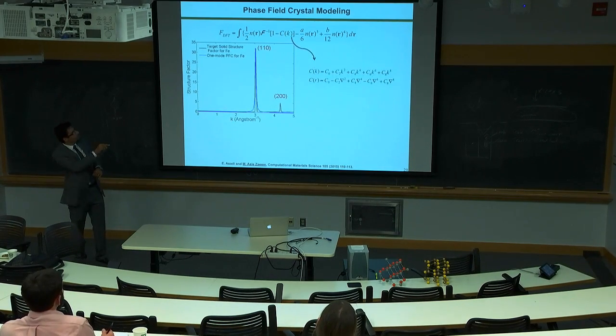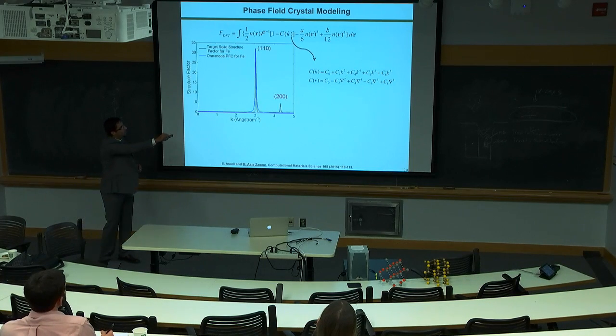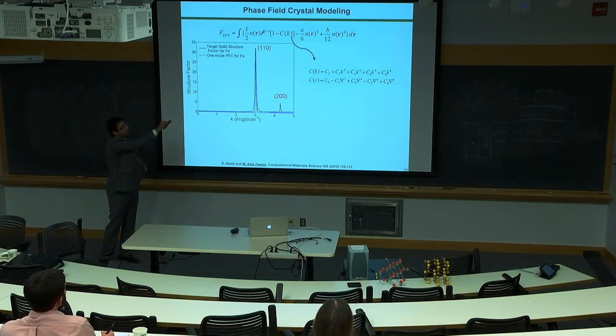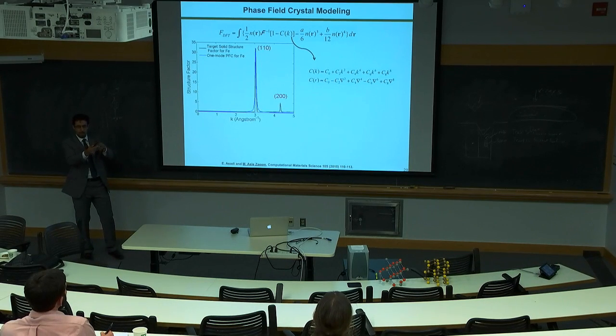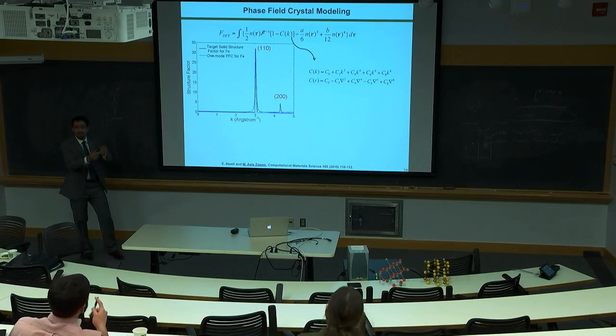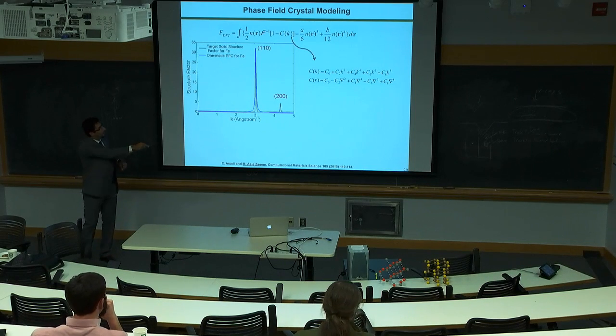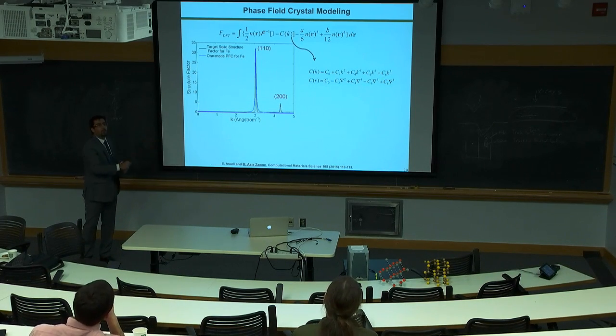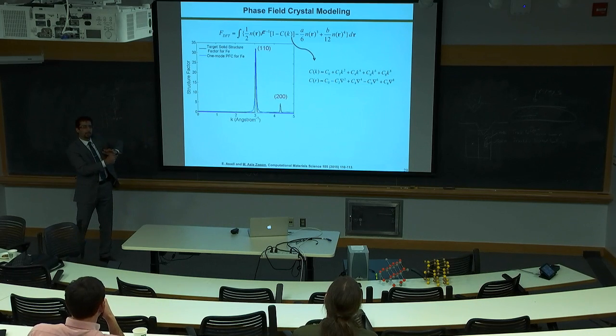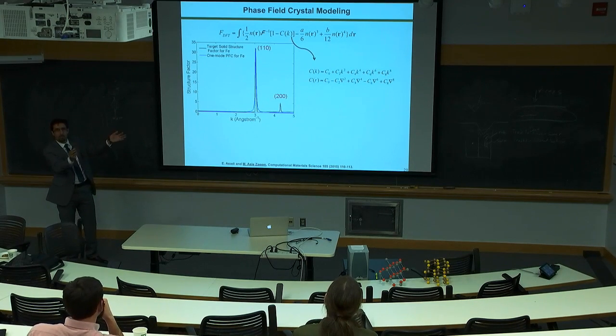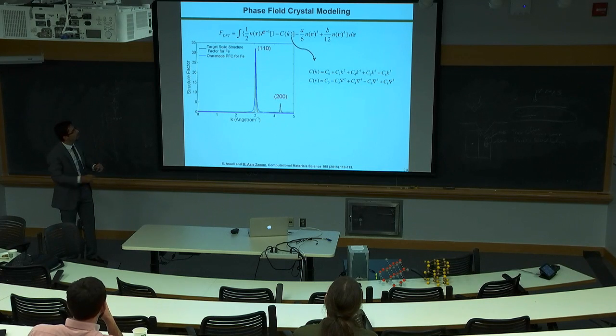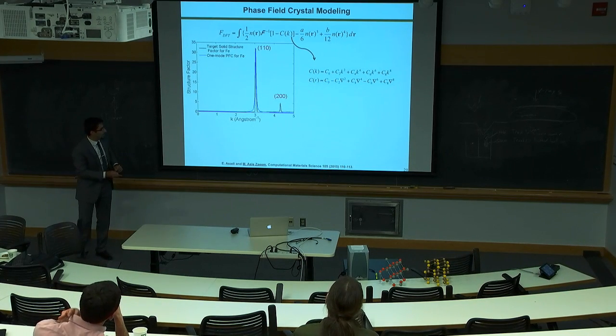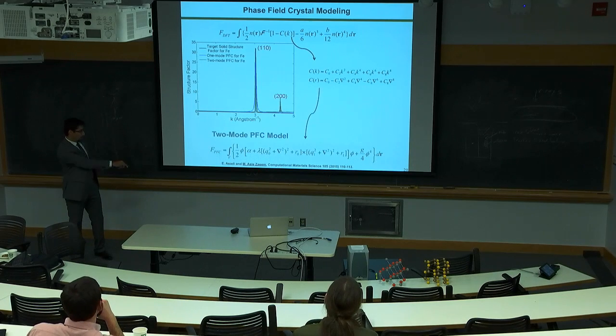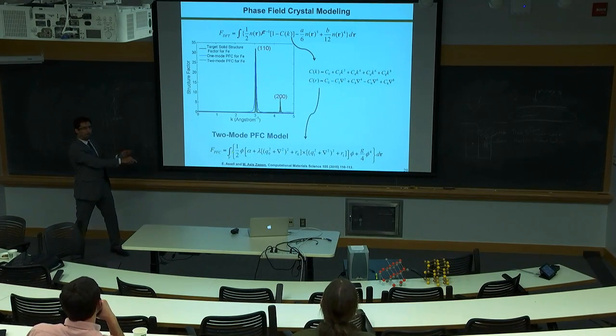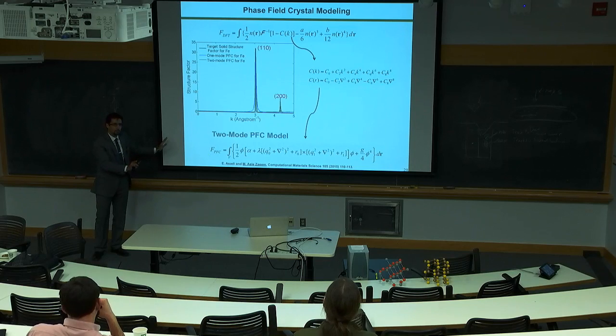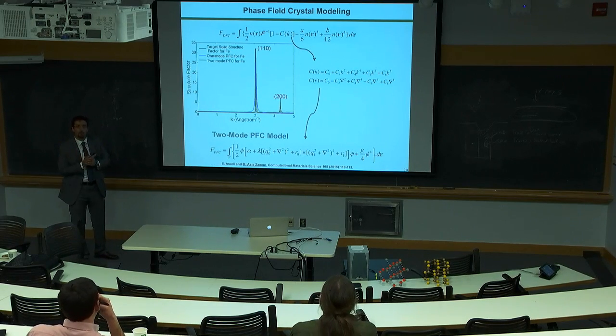But how can we make an approximation of this? If we use a polynomial of 8th order replacing the correlation function, representing the interatomic relationships, in real space it will be 8th order. So this is why we get high order gradients. In Fourier space, it's just a polynomial of 8th order. In real space, 8th order. Replace this here, and you get the phase field crystal free energy. Again, we have a free energy, and then we can go and find our evolution equations.